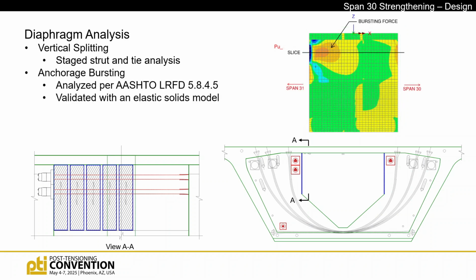Now, we had to, of course, look at bursting here. You can see in the image on the lower right, those anchors are really close to the edge of the diaphragm face. You'll see why here in a minute. But so we designed them, the bursting per AASHTO, but then also went back and did a finite element model just to validate it. And so that's what you see in the top right there. The bursting stress is in orange. We took slices through that and then integrated the stresses to get the forces to calculate the amount of bursting reinforcement we need, and then added CFRP sheet for that additional bursting reinforcement that was required.